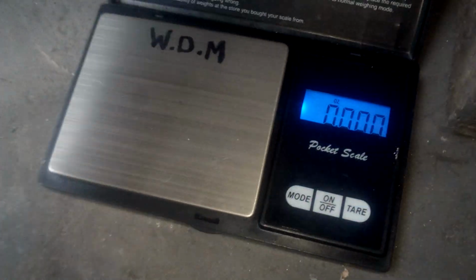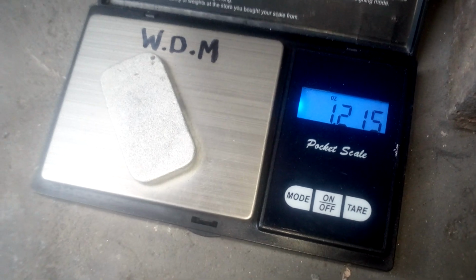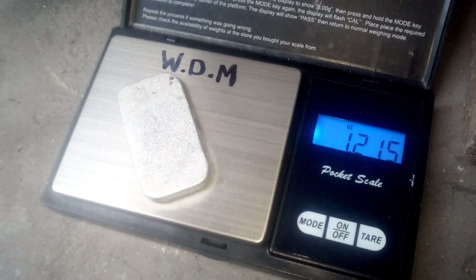High antimony tin alloy. See how much it weighs. Got it set to ounces there. So it weighs 1.2 ounces, so let's say the 0.05 is water yet to evaporate. So, 1.2 ounces. Very shiny bar, very nice. It's actually a lead-free solder type alloy, worth a little bit. And so that was pouring tin antimony alloy. And there's antimony in there. Shiny, strange material.